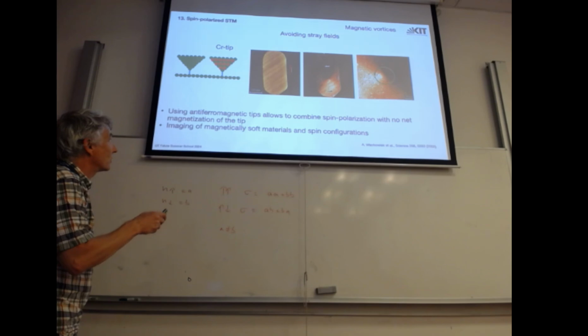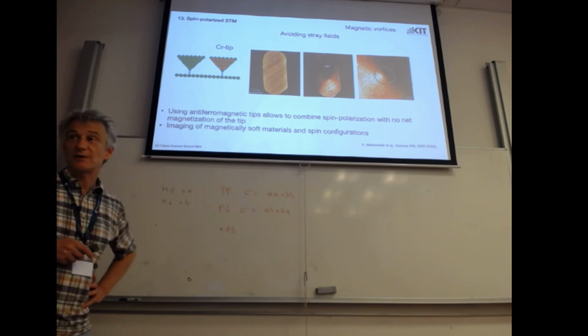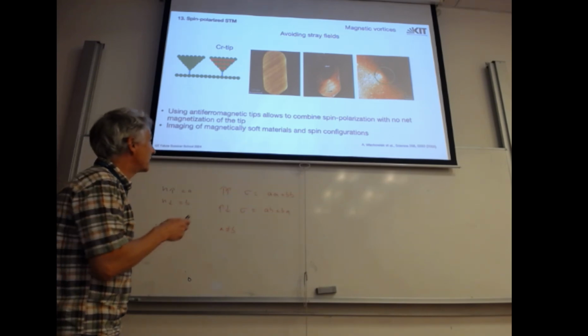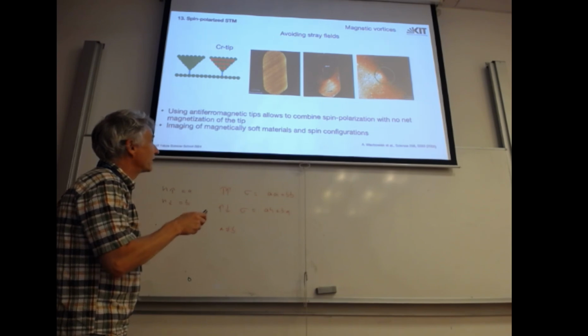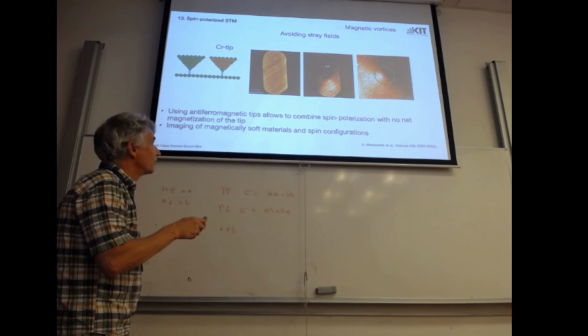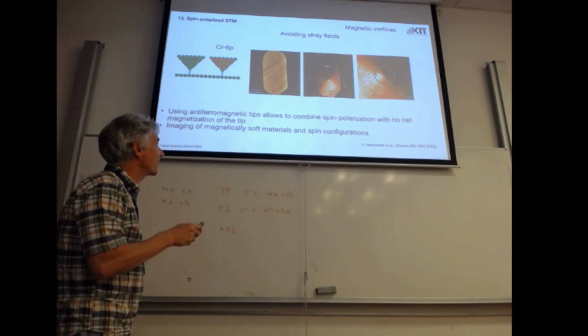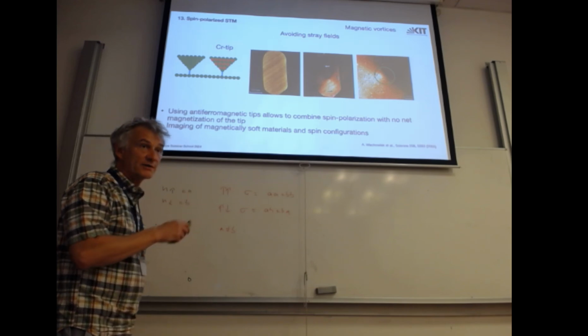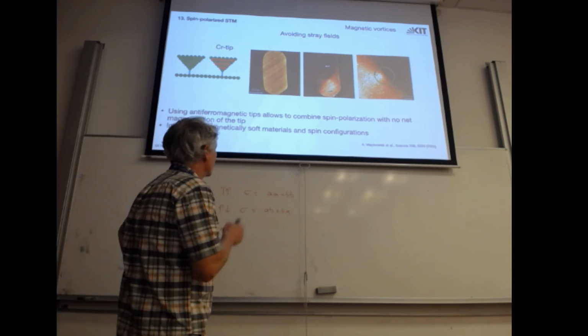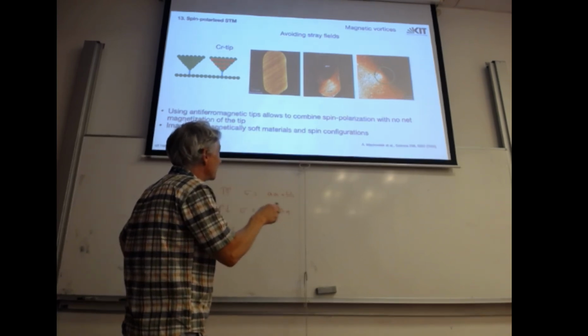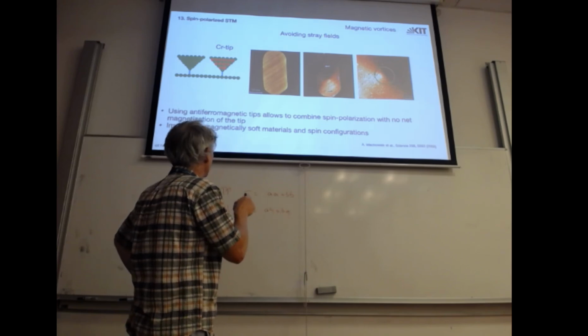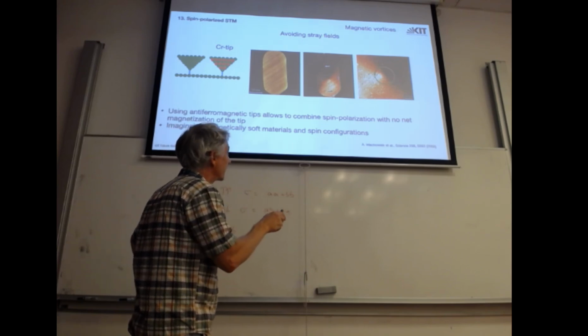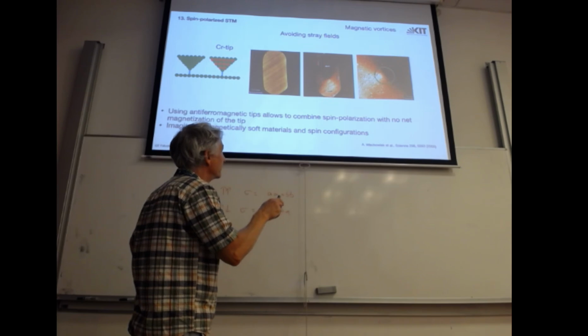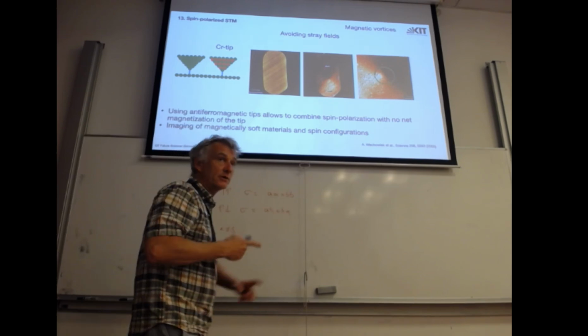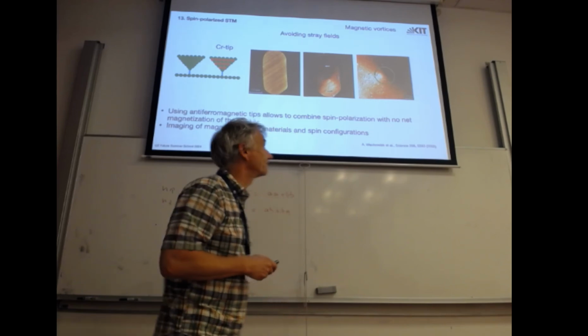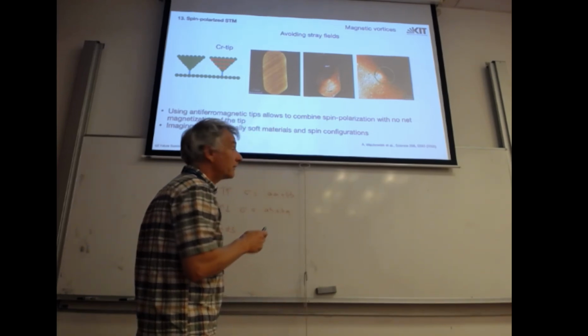They took a small iron crystal. This was done by molecular beam epitaxy. And then you see, to reduce the magnetic stray field, the magnetization will make this vortex state. In some direction, your tip is pointing, maybe to the right. If the magnetization is pointing to the right, we get a large differential conductivity, here minimal. And if they are orthogonal, you get an intermediate one.